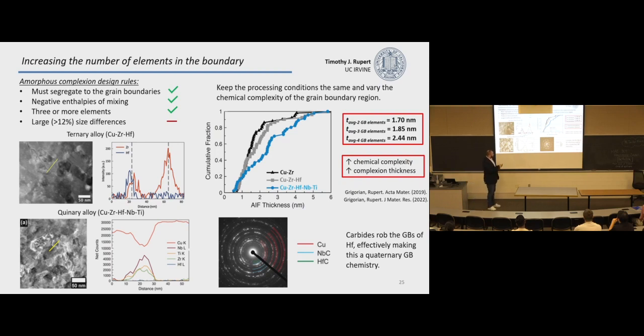a plot like this. So this black plot is what our binary copper zirconium looked like. Most of the amorphous grain boundaries are between 0.5 and 2 nanometers thick. There are a few that are thicker. And as we go from 2 elements at the grain boundary to 3 to 4, we're pushing out to the right, which means we're getting thicker and thicker amorphous grain boundary complexions. So increasing that chemical complexity does tend to increase that complexion thickness.